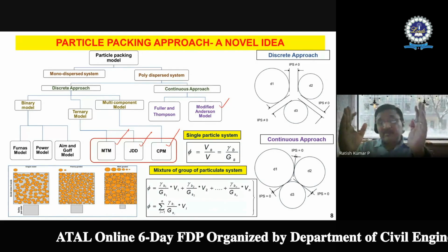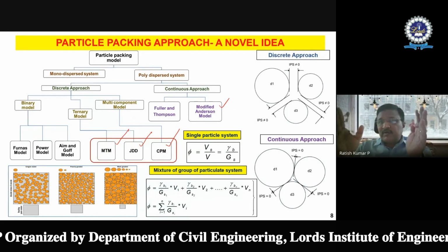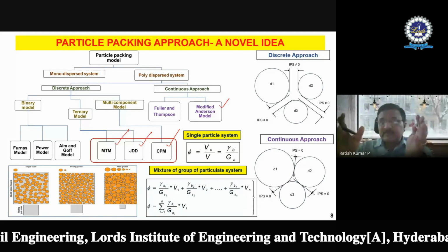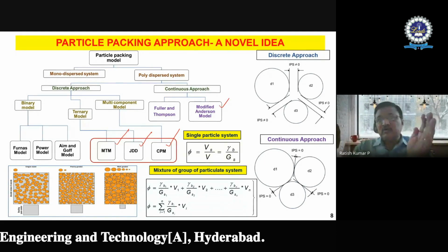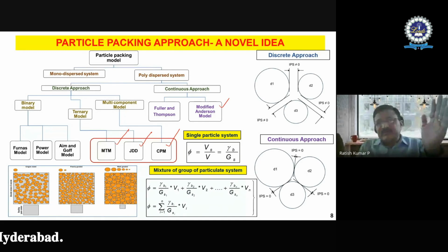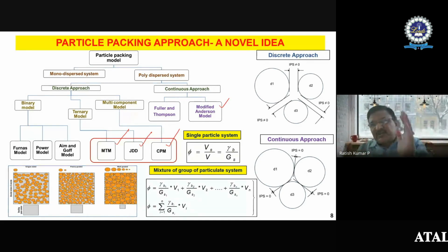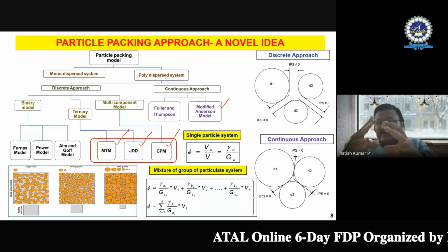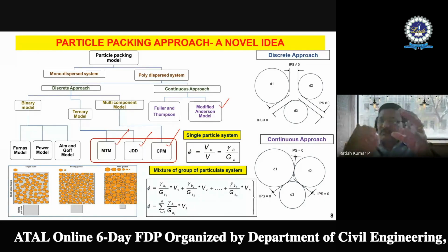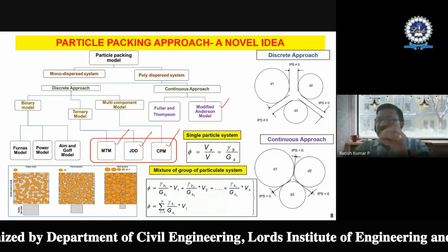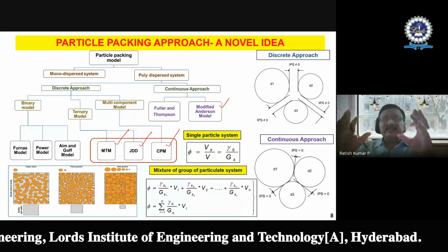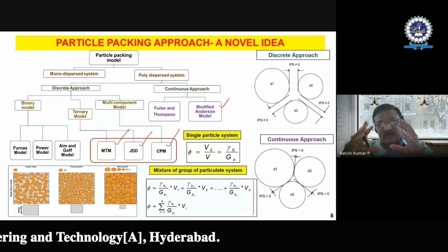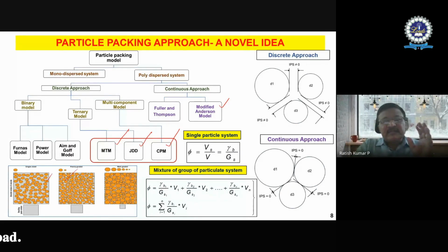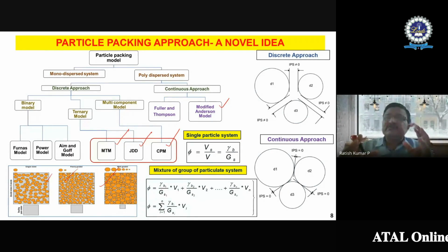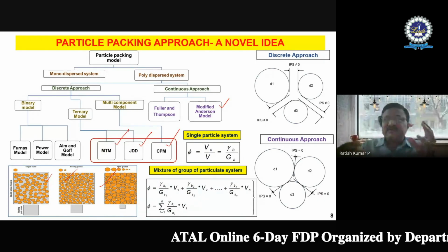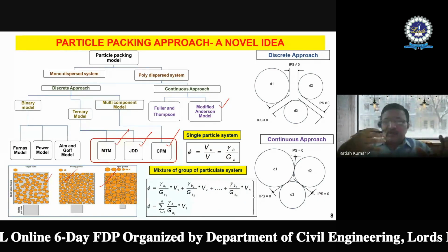One of the important things I would also like to put up is that when I go for crushing plants, I should also give a model to them, because whatever I do should be a practicable thing. So when I do the crushing, it should generate different particle sizes. And if I mix them in a certain fashion, say 50% of this, 40% of this, 10% of this, or 30%, 20%, 10%, 5% of this, what is the best way of adding up the bigger particles and smaller particles, considering the wall effects, the container effects, and the compacting effort, for example.